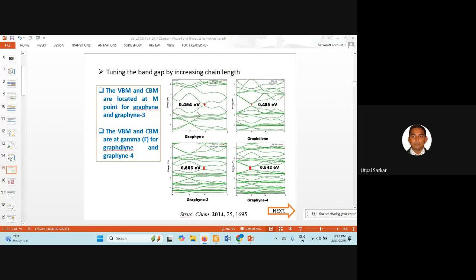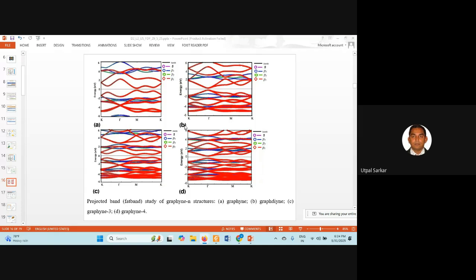Okay, so this is the band structure for graphyne, and then when you are increasing the chain length, graphyne-3 and graphyne-4, the band gap is basically decreasing. But one interesting point here is that for an odd number of acetylene linkages, the band gap is located at the M point. However, for an even number of acetylene linkages, the band gap is transferred to the gamma point. Okay, so all these are direct band gap semiconductors, and this is the fat band analysis of different graphynes. So you can easily identify the energy range and which particular orbitals, px, py, or pz, for which carbon atoms are contributing near the Fermi level.